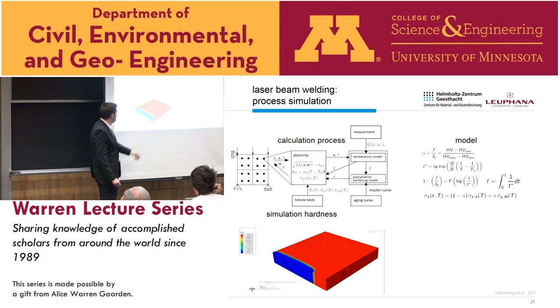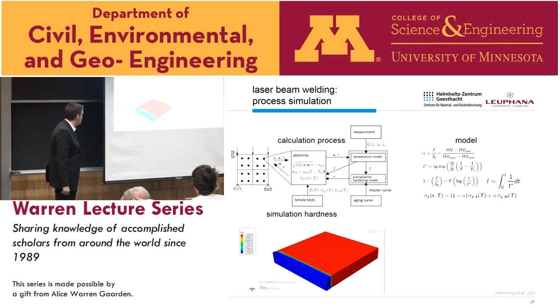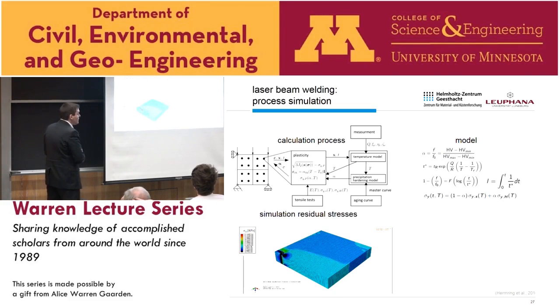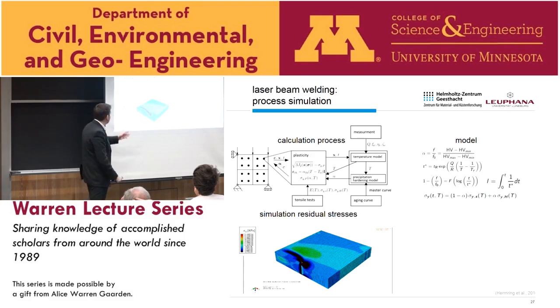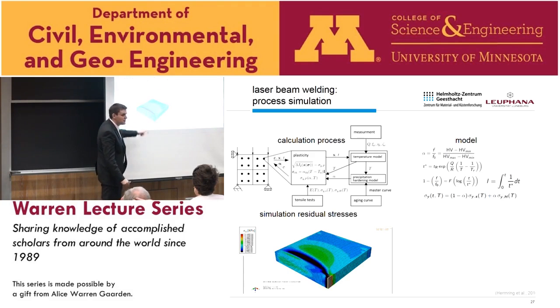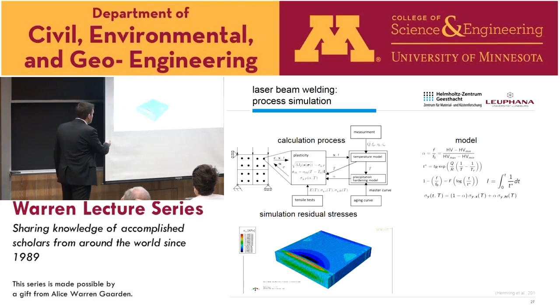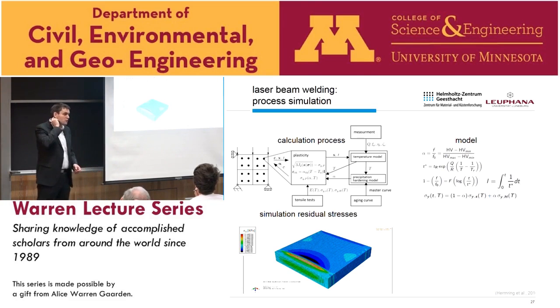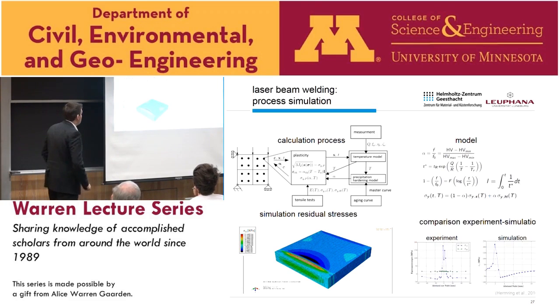tempered state. And by that we could then investigate first of all the hardness. There's no surprise that you have a much decrease here in the fusion zone region, because all the precipitates are resolved, you have a complete melting. But we were in particular interested in the residual stress profile. What you can see is during the fusion process, it first looks like a compression stress state. However, as soon as we have a complete solidified region, we can clearly see there is a high tensile stress region inside of your material. And we wanted to predict this, of course, correctly.